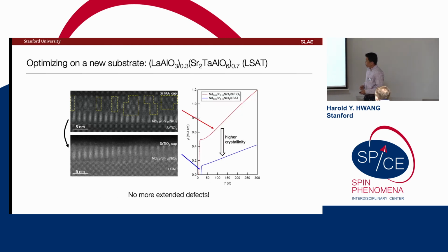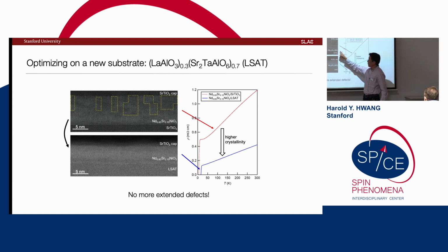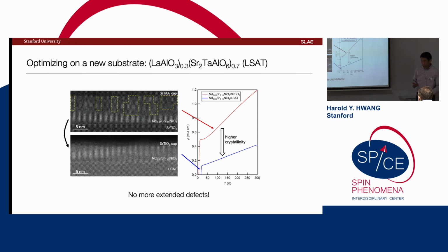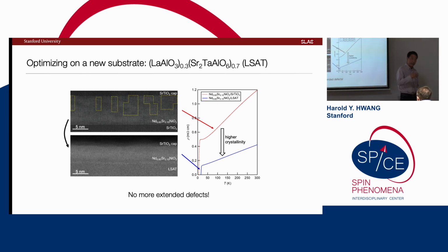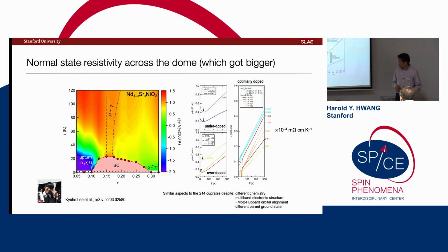And not a shock, actually, if we look at a direct comparison of the same doping level, same thickness, and what have you, we see that the scale of the resistivity comes down quite a bit. In fact, superconductivity is enhanced. And so we think we're at the first taste of looking at what intrinsic transport is doing. Now, there are still a lot of caveats, right? Fairly narrow thin films, so surface and interface scattering are still relevant, et cetera. But hopefully a big step forward.